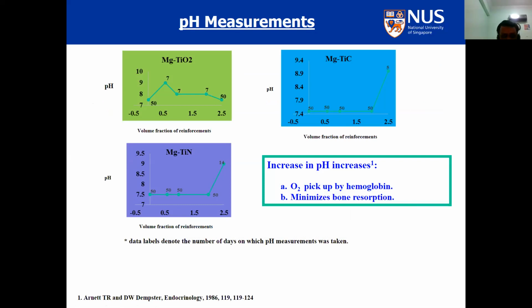You have to do literature search. You have to see what is the best. One of the outcomes of magnesium dissolution in the body is the increase in the pH. You don't want the pH to increase too much. So for example, if you look at this graph on the top left-hand side, you will see that if I put 2.5% of TiO2 for 50 days, my pH increase is only about 7.5 here. So I will choose magnesium 2.5 TiO2.